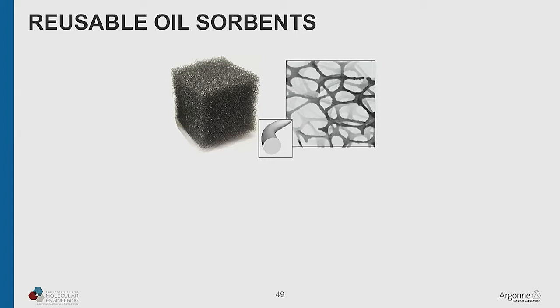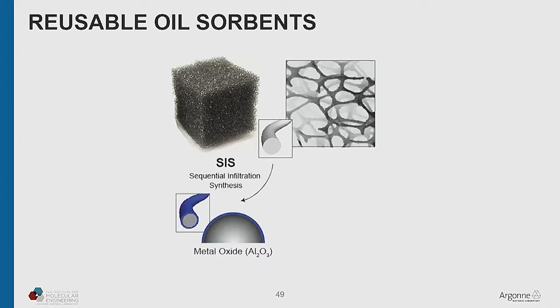It's not very effective. So what we need to do is to change the chemistry at the interface of all the pores that make up that foam to make them love oil and hate water. And the way we do that is a two-step process that starts with SIS. So that penetrates all of these little struts that make up the foam with an inorganic material. Aluminum oxide is one of our favorites, but we've used others too, zinc oxide, for example.